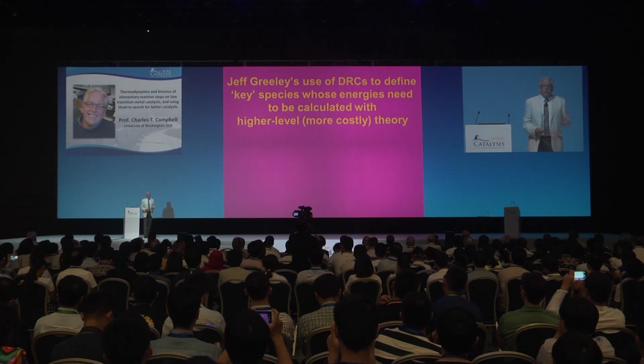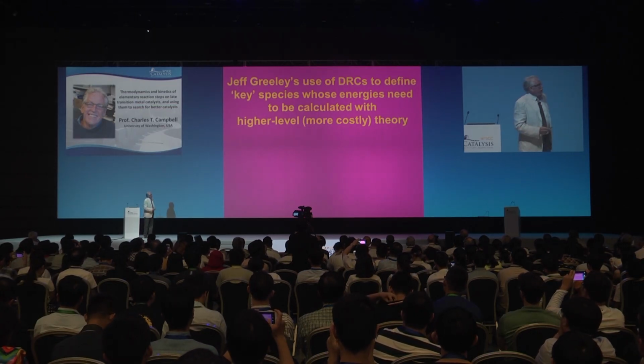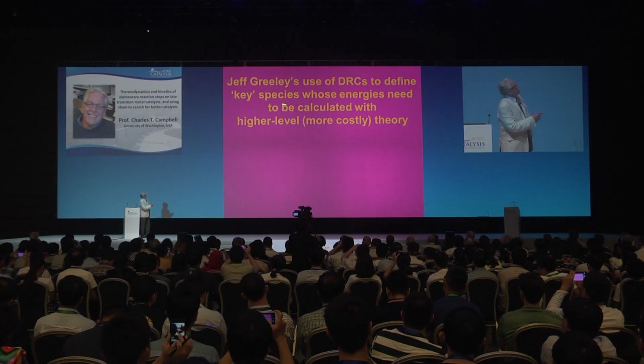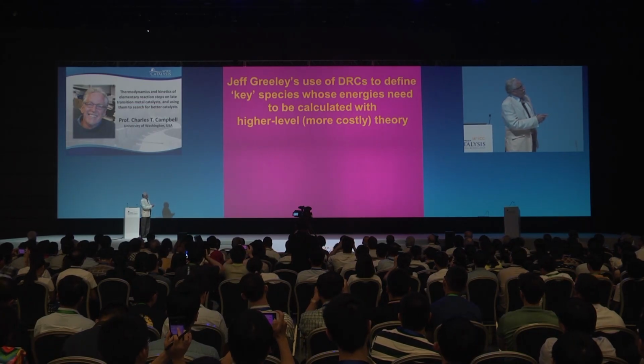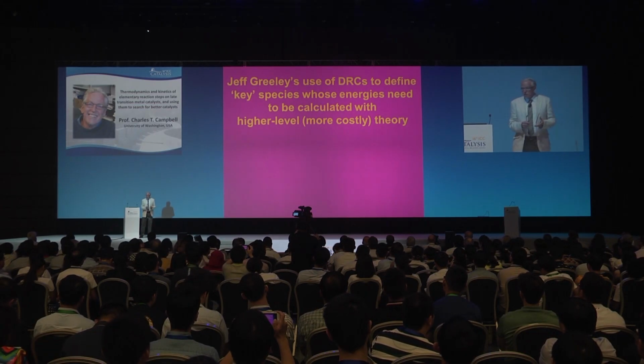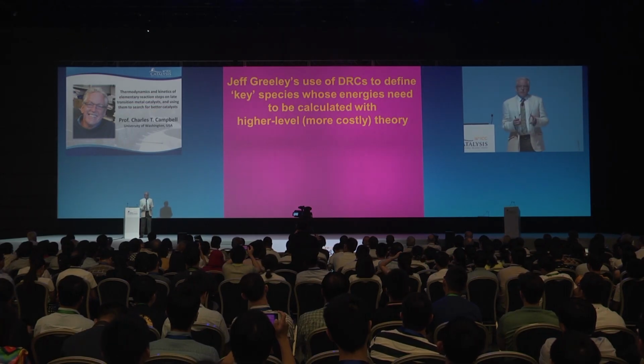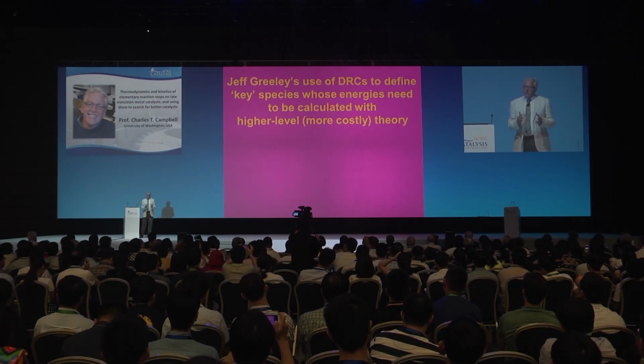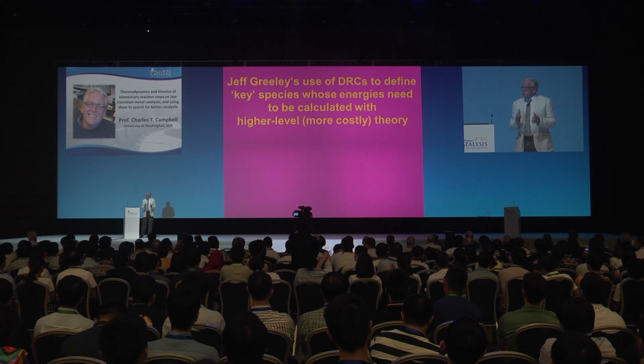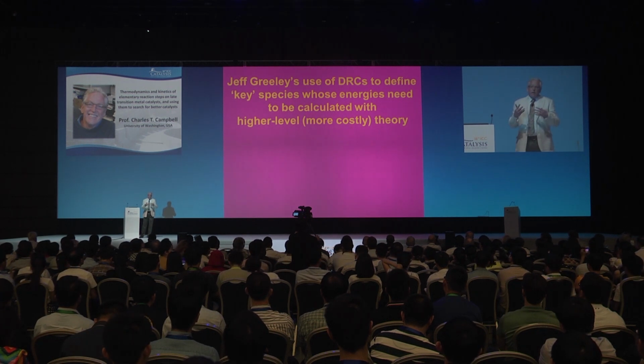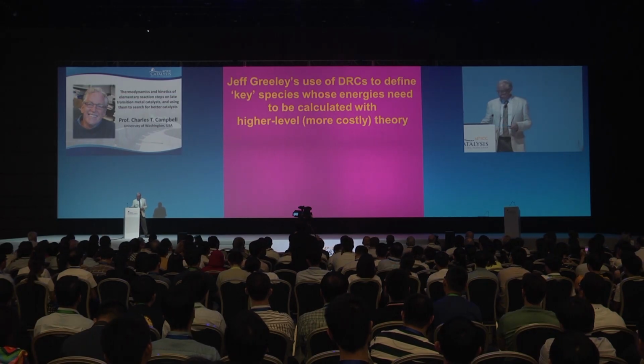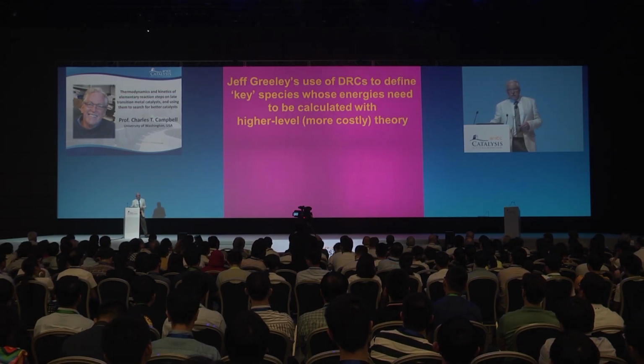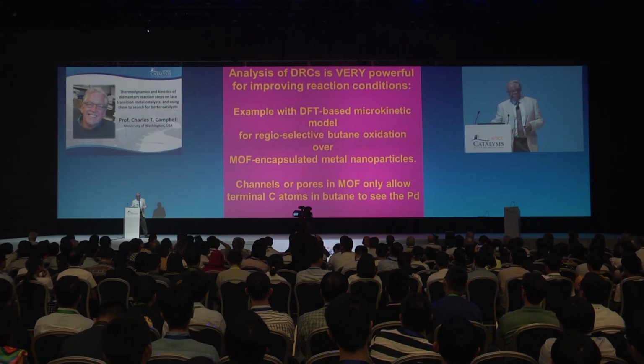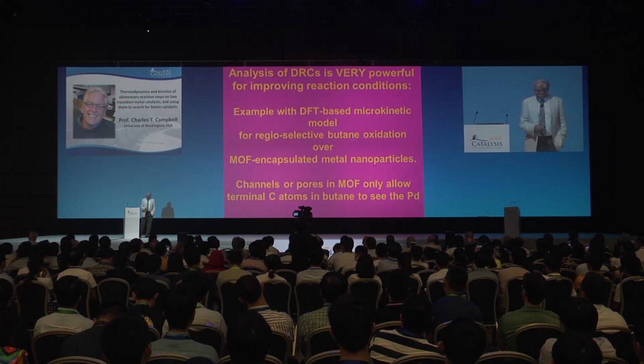and how to study those. I just heard Jeff Greeley speak a couple of weeks ago at the Gordon Conference in catalysis, and he showed that he uses his degrees of rate control in his microkinetic models based on density functional theory to discover which species energies are sensitively controlling the rate, and then he goes to a higher level, more costly version of density functional theory to get better, more accurate estimates of those energetics. So that's a wise use of that.